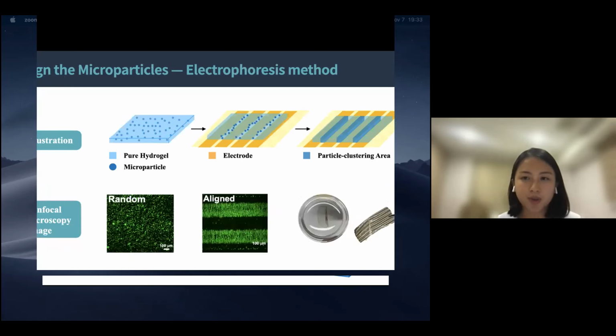So how to control the alignment of the particles? The first step, the particles will be randomly placed in the hydrogel film. Then we will apply the electrical field by placing the electrode underneath the film. Then the particles will tend to cluster in the area where there is no electrode underneath.